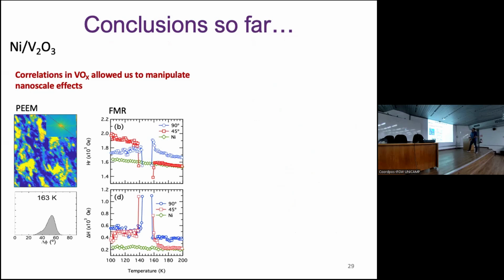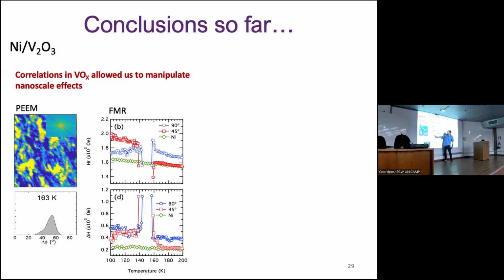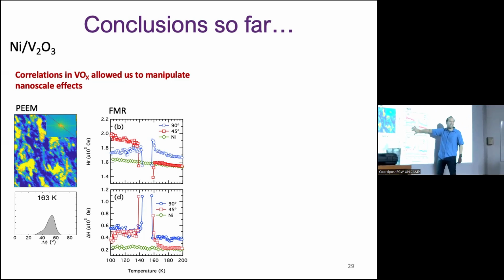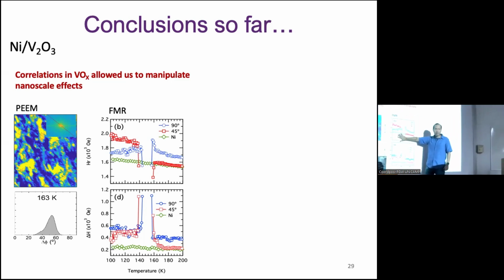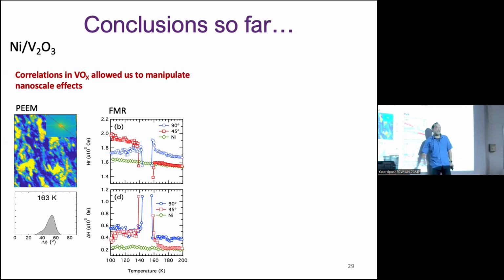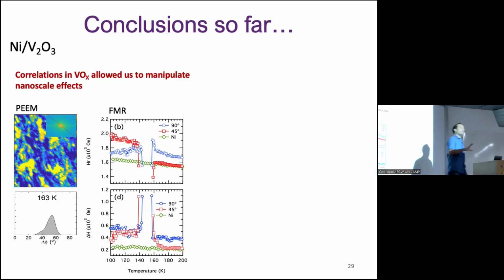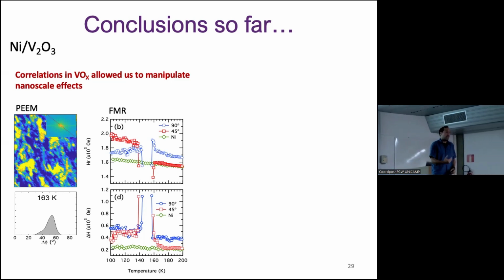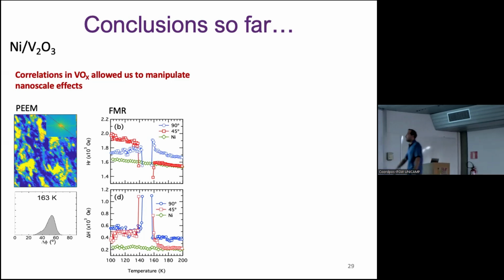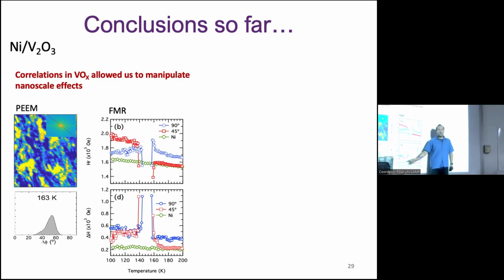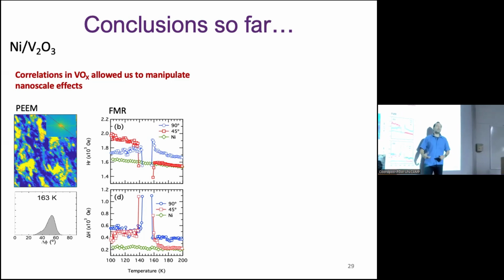So we are basically controlling the FMR. This is the resonance field, and just in the transition, you see that there is a lot of disorder. There is no coherent rotation of the domains. There is no single resonance line, so there is nothing here. So it means that there is no coherent rotation of the domains in the nickel. And if I plot the change, the line width is related to how disordered it is, the dissipation of the processes in the magnetic system. And then you see that this is huge. It means that a spin will precess here very fast, and here almost there will be no precession.